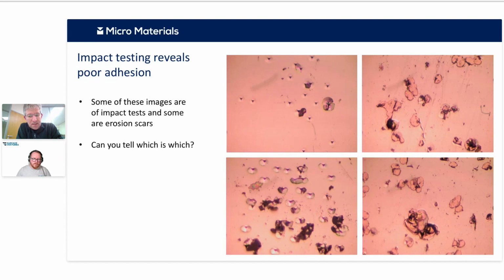The instrument itself is effectively perfectly rigid, or at least sufficiently rigid as far as is concerned. But if you put the same very hard coating on a compliant sublayer or a non-compliant sublayer, then you would be very sensitive to those different mechanical properties, and you can model that out quite clearly. Because that's what you would see in the real erosion test as well. So it's exactly the same thing.